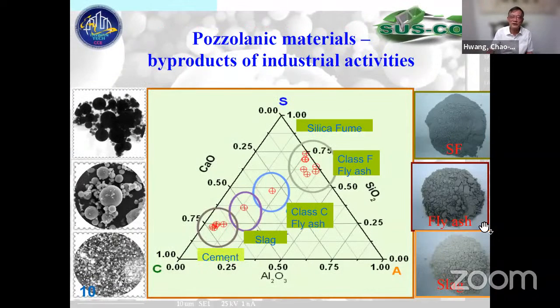Looking at the ternary diagram, SiO2, Al2O3, and CaO, you will see the relationship of class F fly ash, class C fly ash, and slag. In Indonesia there is also a lot of blast furnace slag, which is also very useful. And cement here, and silica fume here. Silica fume is usually needed for ultra high strength concrete, but if you use class F fly ash, you can also have a similar result.